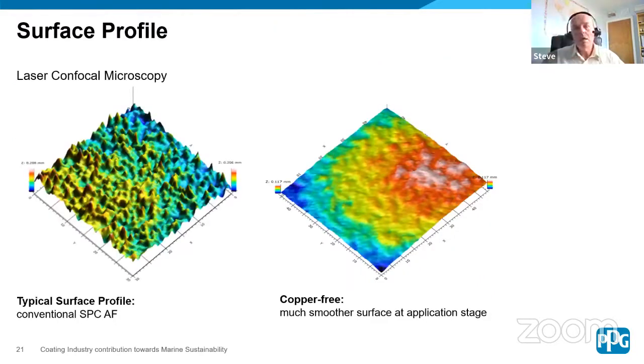We're just coming to the profile. On the left, you see a typical conventional cuprous oxide based SPC. Now, this is obviously a very, very high-powered microscope using laser surface measurements. And you can see the very steep peaks and troughs that are associated with that cuprous oxide granular particle. But in the graph on the right, you see a much smoother, almost flat in comparison, surface profile. So that benefit is immediately there once the vessel returns to service, without the self-polishing, self-smoothing mechanism even kicking into place.